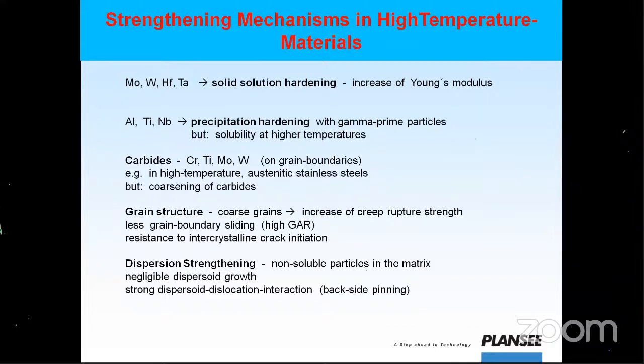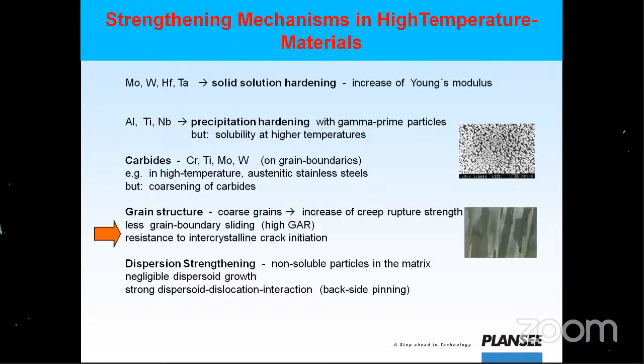But the strength of the material is very low. If you want strength, then you have to add precipitation elements like aluminum, titanium, and niobium. That will work up to something like 850 degrees centigrade maximum. That is the latest alloy development. 718 will go up to 650 degrees centigrade. Then we have another technique: we add carbides. When you add carbon in a limited amount, too much carbon will make it brittle. Carbon in the presence of chromium, titanium, molybdenum, and tungsten forms carbides, which avoid grain boundary sliding and deformation and retain strength. That is one technique. Next is the grain structure, coarse grain. When we have a high grain aspect ratio, it will avoid grain boundary sliding.